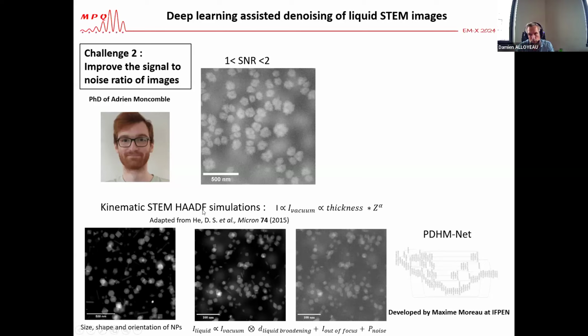So to solve this issue, we try to work with a deep learning denoising approach that has been developed by one of our PhD students, Adrien Moncomble. Adrien has developed an approach which consists in training a neural network with kinematic STEM-HAADF simulations that provide an image without noise, which takes into account only the size, the shape, and the orientation of the various objects that you can create. So it's only a thickness map, and then you calculate the intensity of your nanoparticles through this very simple equation. Then you also give the network a noisy image that takes into account the spread of the beam due to the liquid, the high level of noise due to the liquid cell sample, and all the out-of-focus objects that you can add to your image only by changing the size of the beam that images those objects.